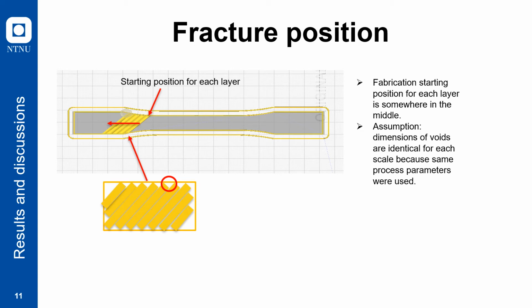And this is one possible reason to explain why some of the specimens have the fracture position near the edge of the gauge length. For the printing, the Cura software, instead of starting from the end, actually starts somewhere in the middle for every single layer. So that may cause some defects in here. And we can make an assumption here. The dimensions of the voids are identical for each scale because the same process parameters were used in this case.